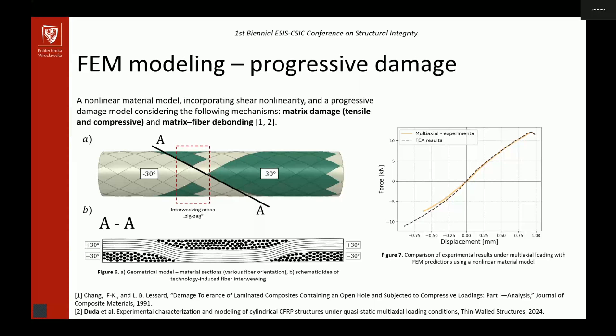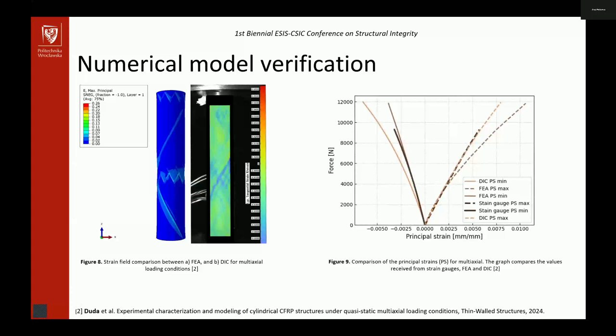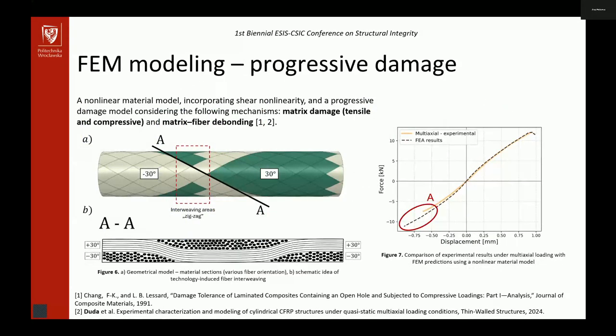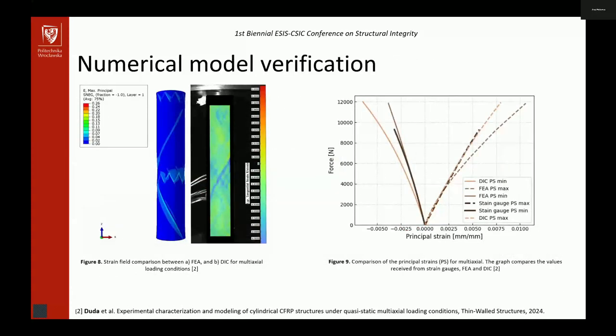You can see the comparison of the numerical results with experiments. You can also find the data on it in our paper in Thin-Walled Structures. So there is this region A. The problem is actually with compression, because this model does not include the defects. Therefore, the numerical model overestimates the experimental results in this case. Okay, maybe two words more about it. The model includes a nonlinear shear material model with progressive damage.